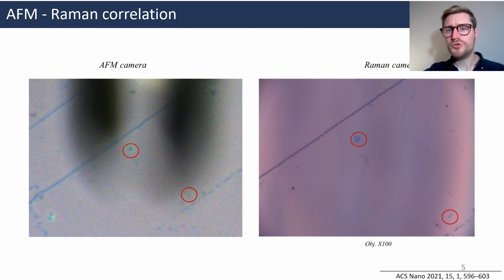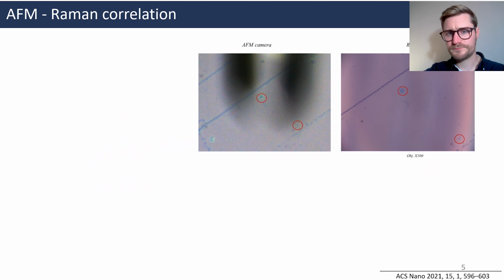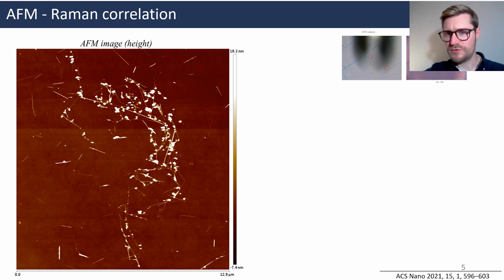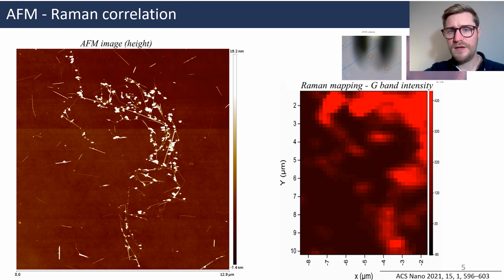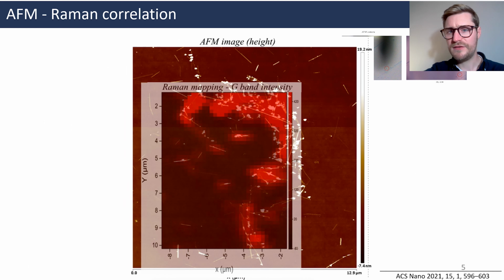We then deposited a drop of the solution on a silicon wafer to do atomic force microscopy and Raman spectroscopy. Those two machines were completely independent, but we managed to find the same zone. Here, the topographic AFM image. We see elongated objects, which are carbon nanotubes, either cylindrical or flattened. Here, a Raman mapping of the same zone. On this image, a Raman spectrum has been taken on each pixel, and the color intensity of the pixel is adjusted according to the G band intensity. As you can see, those two images are perfectly overlapping. This means that we can, in principle, attribute the Raman spectrum to each single object.